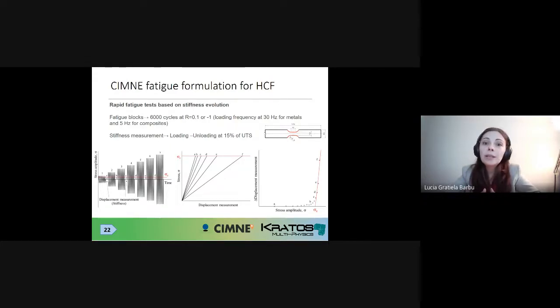And what they are doing is that after each of these loading blocks, they are doing a loading and unloading of that specific specimen at 15% of the ultimate tensile strength. This is done to detect the change in stiffness inside the material. And you can see here, for instance, that the loading history for this type of test has a progressively higher stress amplitude applied on the specimen.